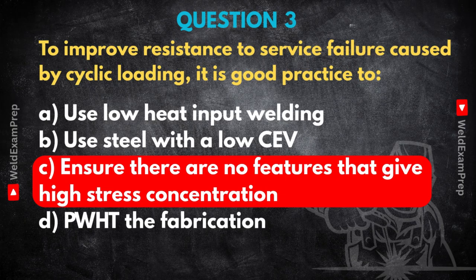Absolutely. But often when fatigue comes up, people also talk about PWHT, post-weld heat treatment, to relieve stress. Why is avoiding stress concentration generally seen as more fundamental for preventing fatigue initiation than PWHT? That's a great question, because PWHT is important, but for slightly different reasons in this context. PWHT is excellent for reducing residual stresses left over from welding. Right, the stress is locked into the material. Exactly. And those residual stresses can influence fatigue life mostly by affecting the mean stress level, which impacts how fast a crack grows once it's started. Okay, so more about crack growth.